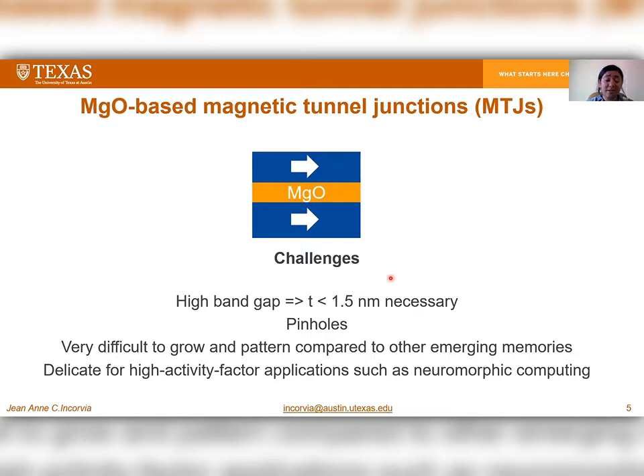Although MgO is the leading tunnel barrier, there are several challenges and limitations restricting it for wider applications. One very important challenge in MgO junctions is that MgO has a very high band gap. This band gap requires a barrier thickness of less than 1.5 nanometers to have an optimum RA product.